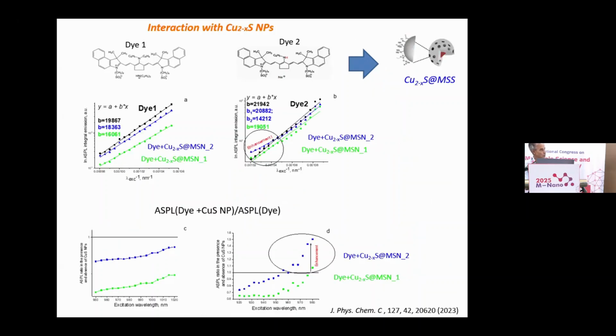For the other nanoparticles, the copper sulfide nanoparticles: the previous slide was shown for interaction of dyes with gold nanoparticles, and this slide shows the interaction of these dyes with copper sulfide nanoparticles. So again, we used two different kinds of copper sulfide nanoparticles with different shells, and for this dye, we didn't observe any enhancement. Here you can see the ratio of anti-Stokes emission in the presence of nanoparticles to emission without plasmonic nanoparticles is smaller than 1. That means that there is no enhancement. But for the second dye, we observed enhancement at specific excitation wavelengths. And this enhancement reached 50%, which is a very good number.